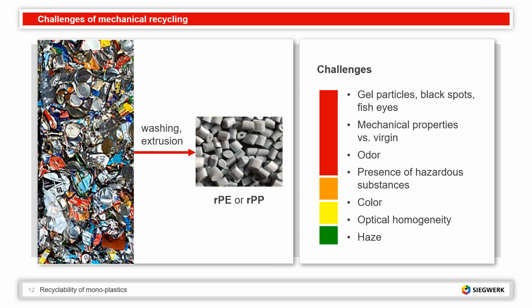Then we have to face, of course, differences in the mechanical properties of a re-extruded film compared to virgin material. It's about odor, also the presence of hazardous substances, if we recycle all the print designs, all the colors together with a monoplastic material. And there are also challenges like the coloration by the colored pigments, or if you look at transparency, homogeneity of the film, sometimes you have to face a certain haze and make some compromises in the end if you want to go ahead. So those are the challenges.